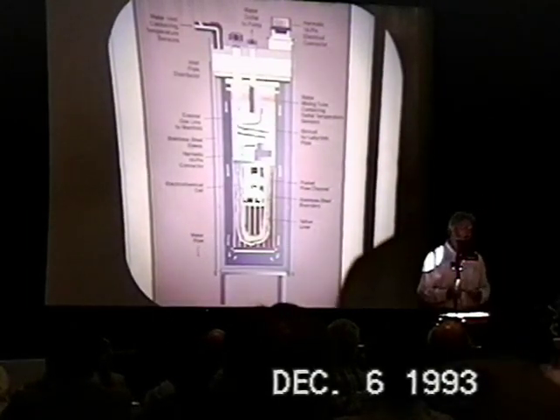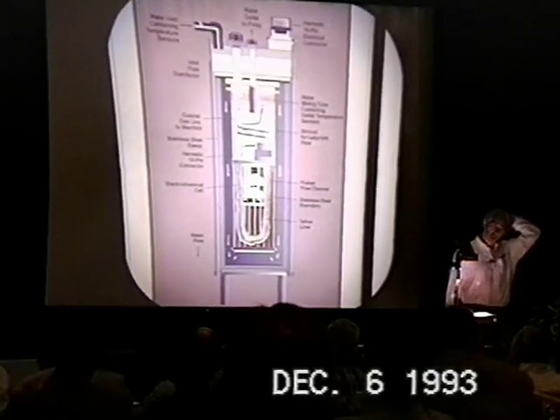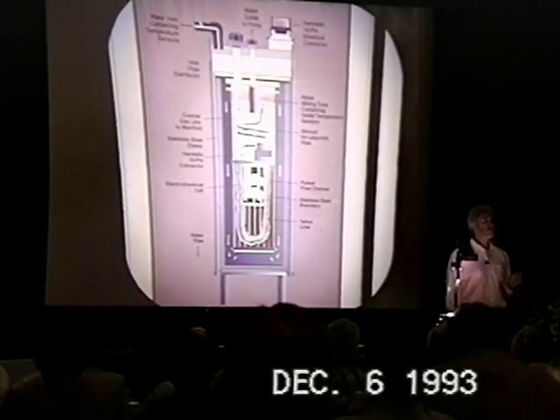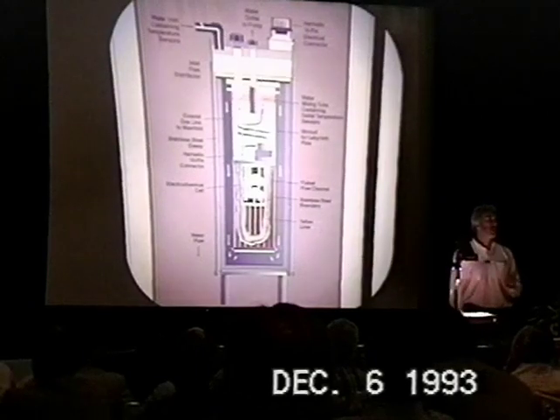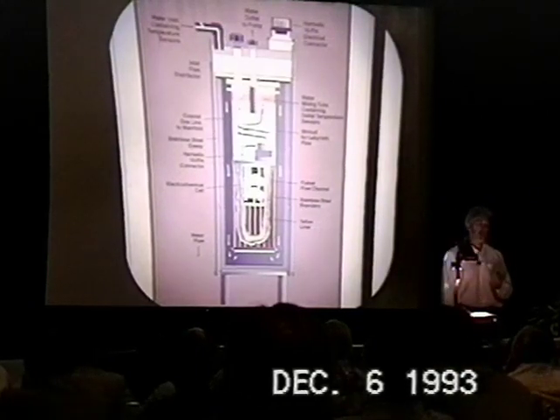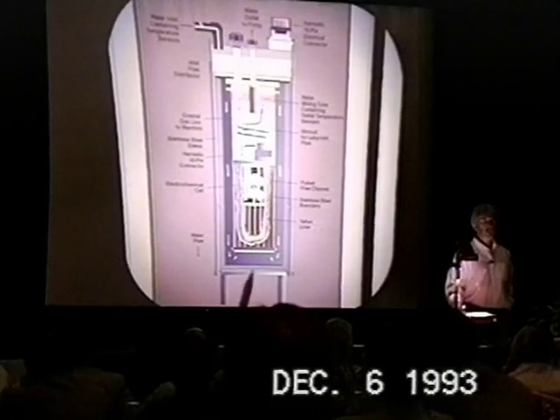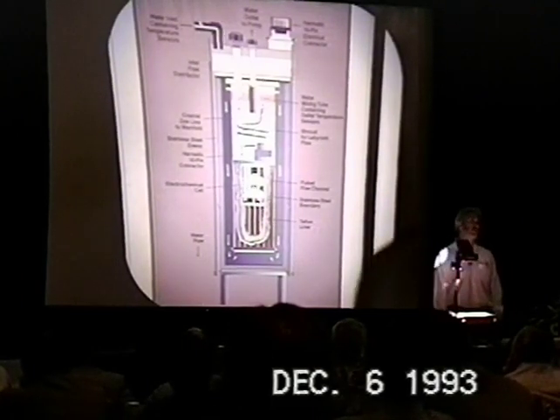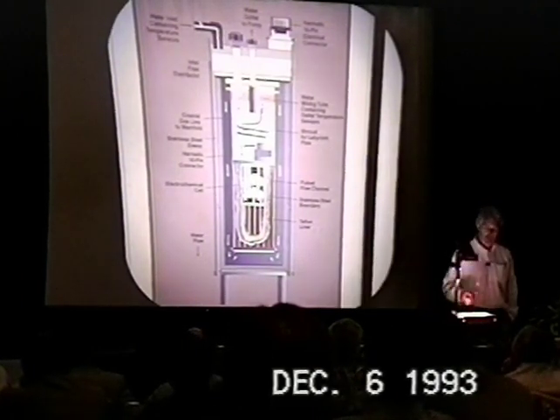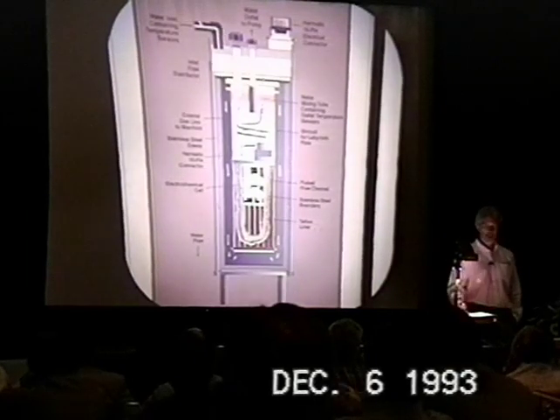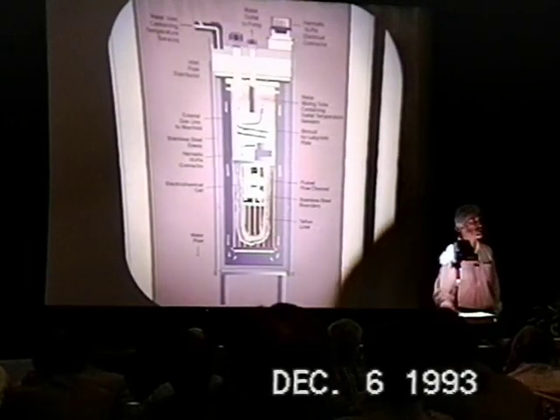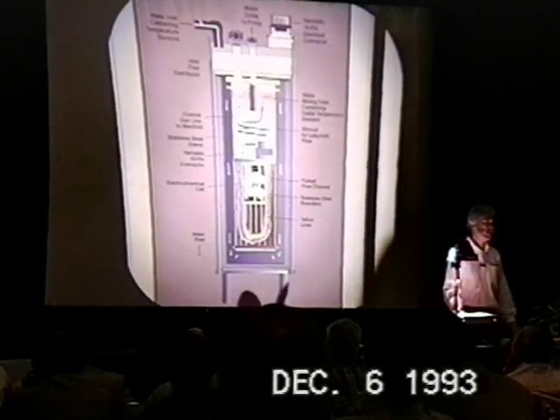By incorporation of this change and some other changes, we were able to get the conductive component of heat flow from the system down below 1%. So in this machine, 99+% of the heat is conveyed as temperature rises in the water. Less than 1% is lost by radiant or conductive methods. So, a very nice result.